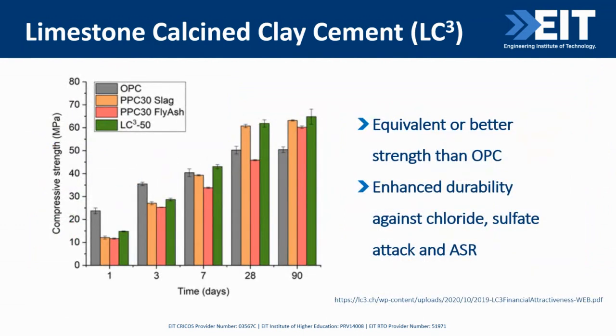And most importantly, performance of LC3 is equivalent and many times better than that of ordinary Portland cement. As we can see from this figure, LC3, which is the green color ones, reaches slightly lower values than OPC at 1 day. OPC is the gray color one. So at 1 day, the strength of LC3 is lower than OPC, but it catches up at about age of 7 days.